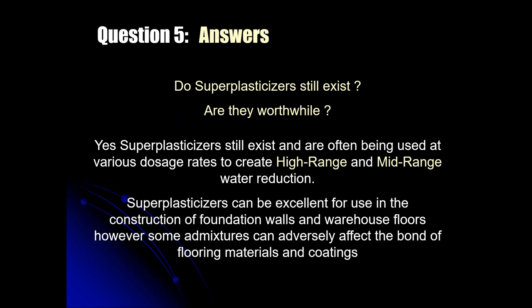But some of the newer generation of admixtures, and I'm not talking about the moisture mitigation admixture, I'm just talking about concrete performance admixtures, have demonstrated some adverse effects as it relates to floor coverings and coatings. Some of these sulfonated... I was involved in a million-dollar issue out in a hospital in San Francisco because of a new class of admixture that was put in the concrete. Again, these are not the silicates. These are just regular ready-mix type admixtures for concrete performance. I'm not going to mention names, but they weren't able to stick to the floor. And then they spent an extra $1 million on this project getting that floor to a condition where they could properly adhere the flooring.